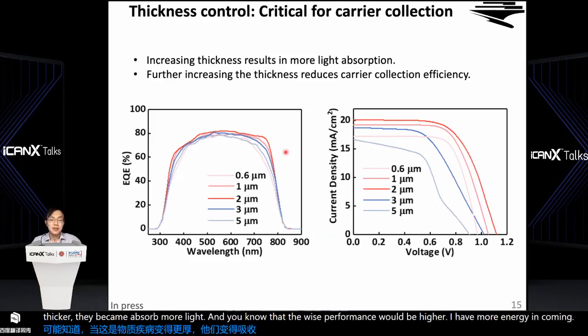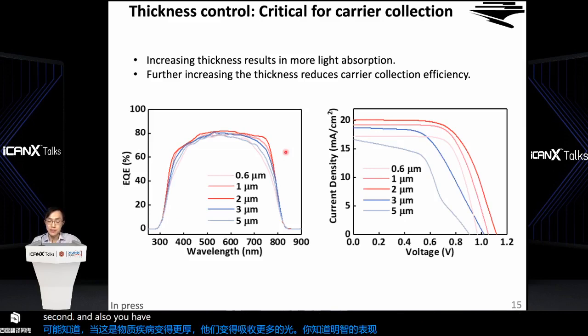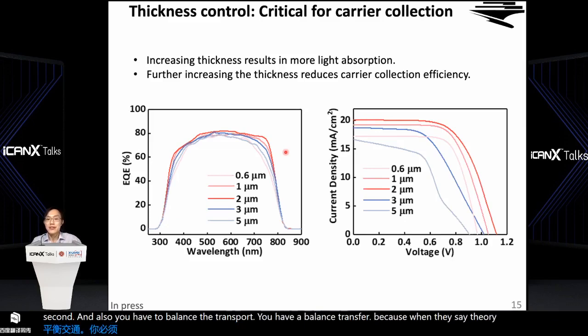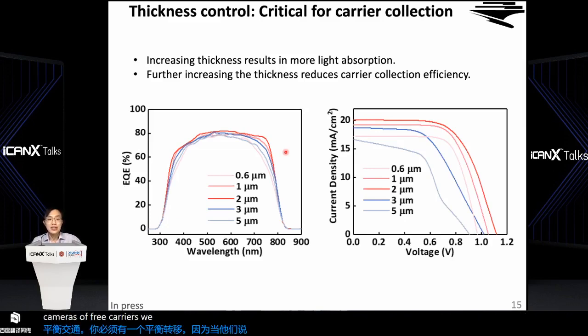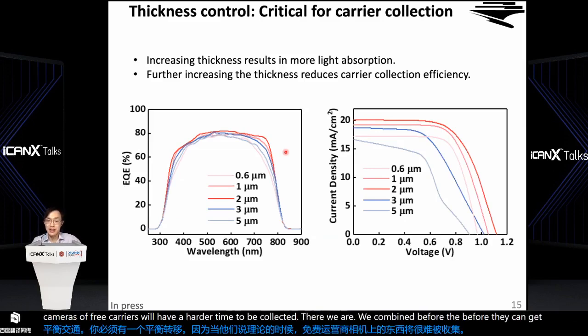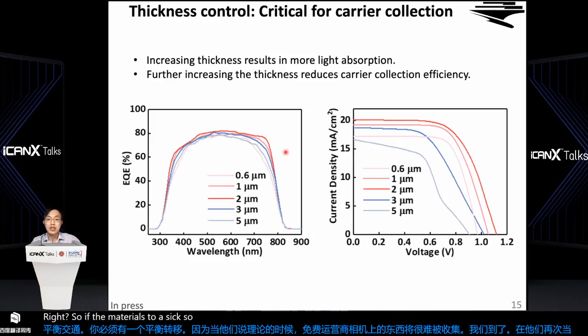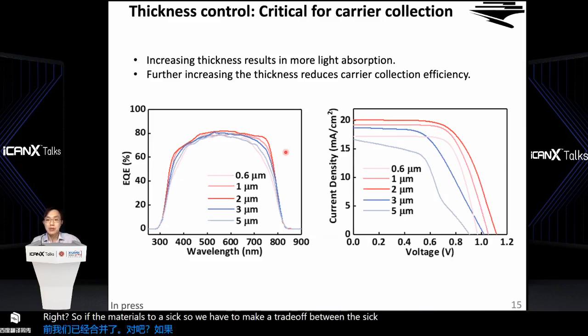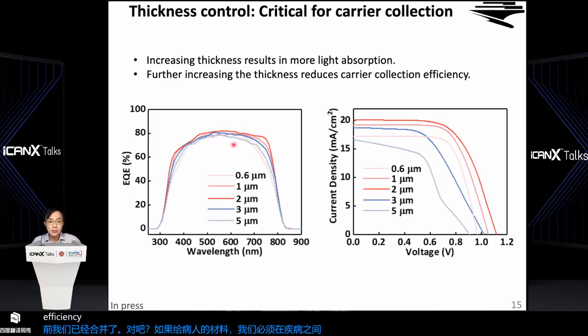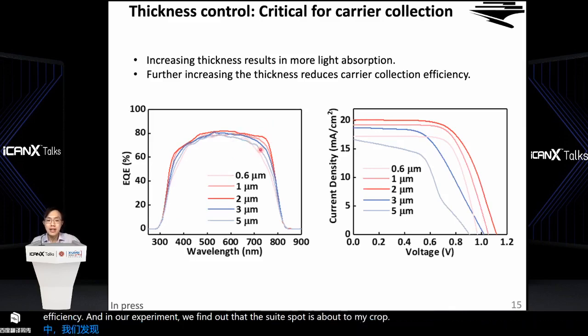The second, you also have to balance the transport, because when this material is thicker, the free carriers will have a harder time to be collected. They will recombine before they can get collected, right? So if the material is too thick, we have to make a trade-off between this light absorption and the collection efficiency. And in our experiment, we found out that the sweet spot is about 2 micron. 2 micron can give us the best external quantum efficiency and also the best solar cell efficiency in this JV curve.